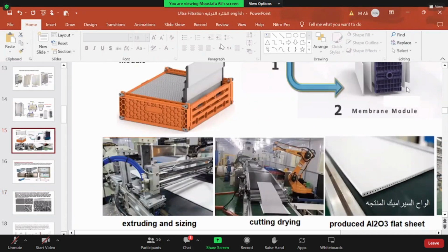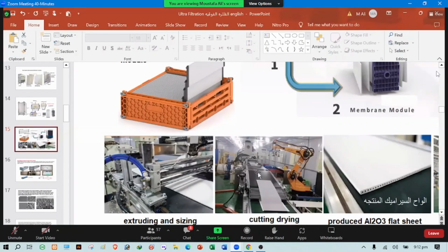I will explain what I already saw in one factory, the flat sheet membrane, just as I said, held in a vertical position. Then the robot started to spray a colorful solution with very fine particles of alpha aluminum oxide, also 1 micron particles. Let's say the first layer will be 5 micron particles, just to build the outer layer around this 10 to 50 micron particles. So the robot holds it, fixes it in vertical position. It goes in the production line.